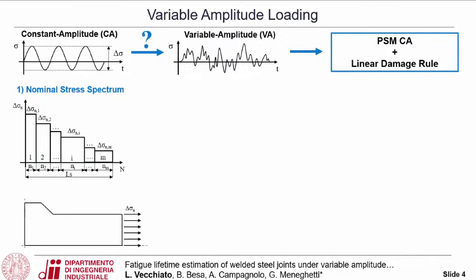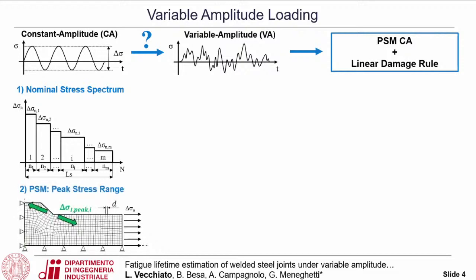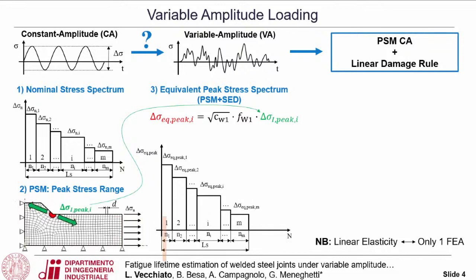The first step is to know the nominal stress range spectrum and the local geometry of the welded details, as in the example. The second step is to apply the peak stress method for computing the singular stress at the V-notch tip, the nodal value at the V-notch tip. And then, combining the fatigue strength criterion of the strain energy density, it is possible to define the equivalent peak stress range for every nominal stress range of the spectrum. Please note that to define the equivalent peak stress spectrum, only one linear elastic finite element analysis is required.